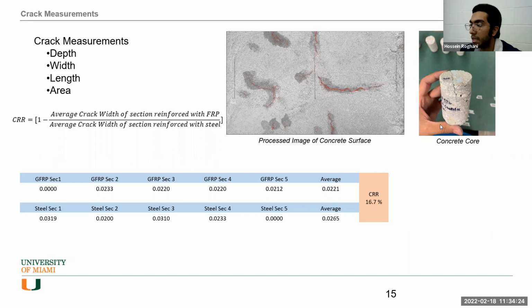For example, in the core that you can see here, it almost penetrates half the depth of the slab, and the slab was almost 4 inches. So I assume that it penetrates 2 inches, and the rebars are at a depth of 3/4 inches. So for sure, I can say that the rebars are engaged. And the crack quantification is done by image processing techniques, as I mentioned before, to measure the widths, lengths, and area.